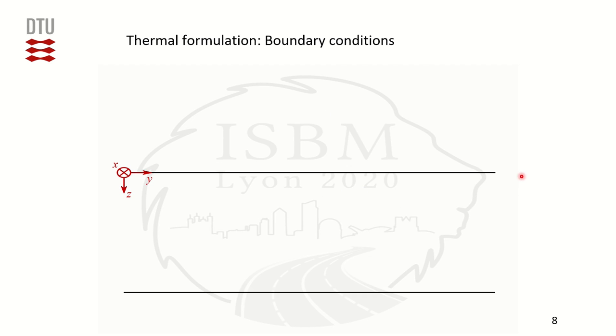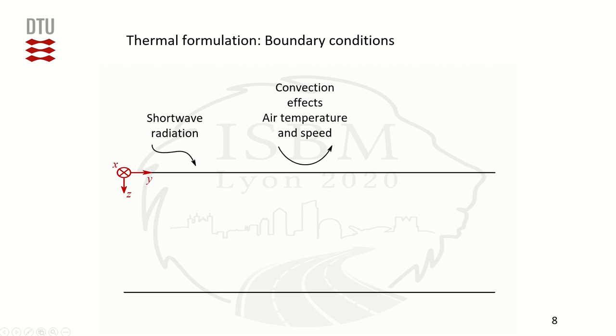Here represented is the model half space. The upper boundary consists of an energy balance at the surface, controlled by synthetic weather effects. In this work, the short-wave radiation, convection effects originating from the airspeed and the air temperature, as well as the long-wave radiation are considered. The wind speed is taken as constant with a value of 10 km per hour. The long-wave radiation is split between the downwelling and upwelling contributions.